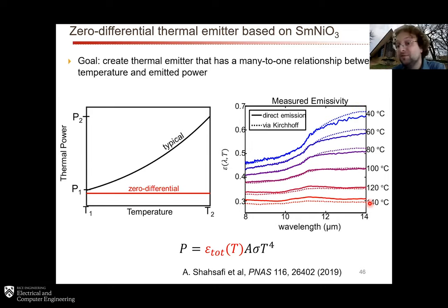Actually, the rate of this decrease is almost perfect, because we want to almost exactly cancel out this temperature to the fourth dependence, and it turns out that this is just right. So when you integrate this curve over wavelength and you get the total radiance versus temperature, you can see the units are well-defined, and there's this region for the zero differential emitter from about 100 degrees to about 135 degrees where the curve is completely flat. So no matter what the temperature is, the amount of thermal emission is the same, or the emitted power is the same.